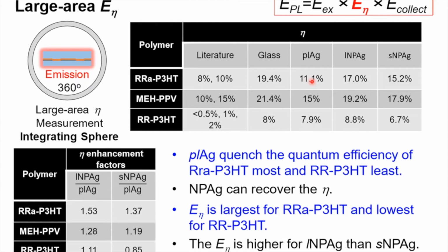On planar silver, this dropped for the two more amorphous polymers, and it stayed about the same for regioregular P3HT. For the two porous metasurfaces, the large and the small pore surfaces, we found that in general we were able to recover some of the emission that was quenched by the planar silver, up to about 17%, almost the same as glass, for the large nanopore silver.